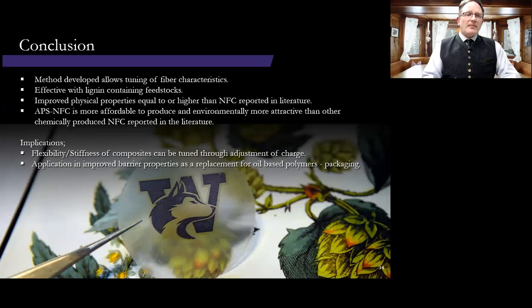So to conclude, the methods that we developed allowed us to engineer and tune specific fiber characteristics of NFC. It was effective at oxidizing lignin-containing feedstocks. We got an improvement in physical properties that was either equal to or higher than what's been reported in the literature for NFC. And ammonium persulfate produced nanofibrillocellulose is far more affordable to produce and more environmentally attractive than other chemically produced nanofibrillocellulose. Some of the implications for this, particularly with, say, composites, if you just wanted to change the flexibility or stiffness, the only factor that we may need to change is surface charge.